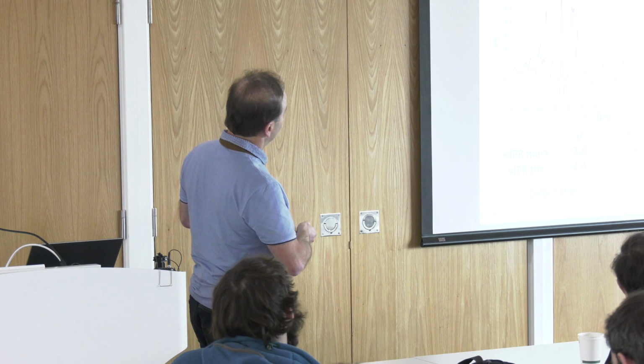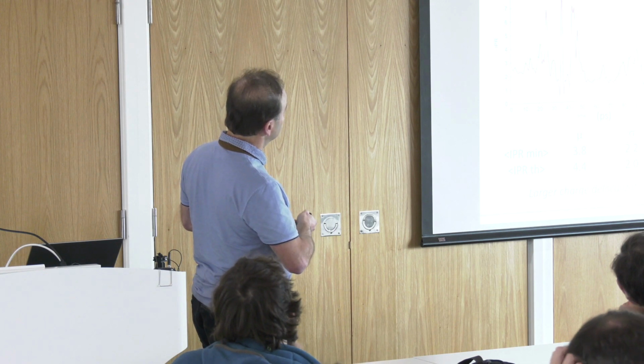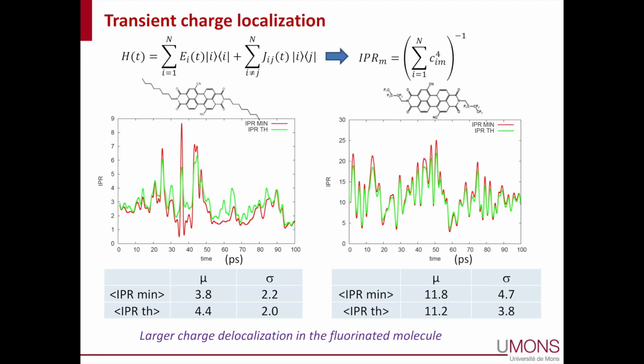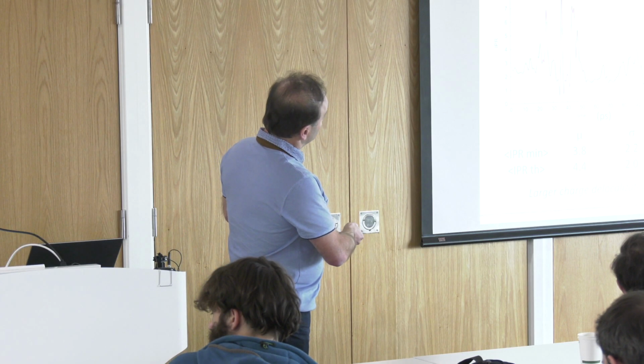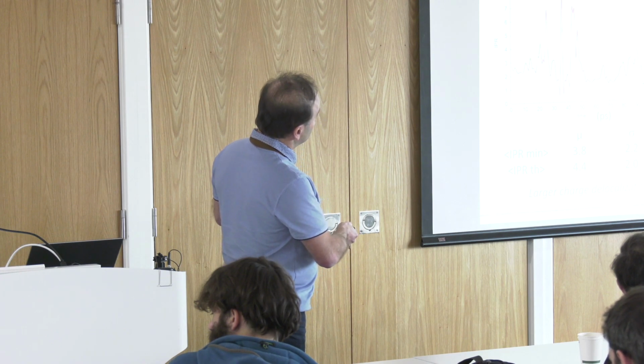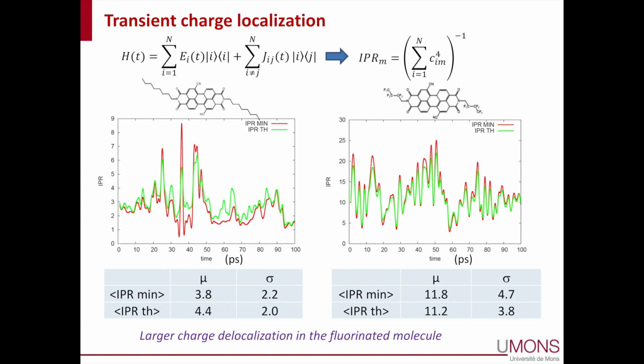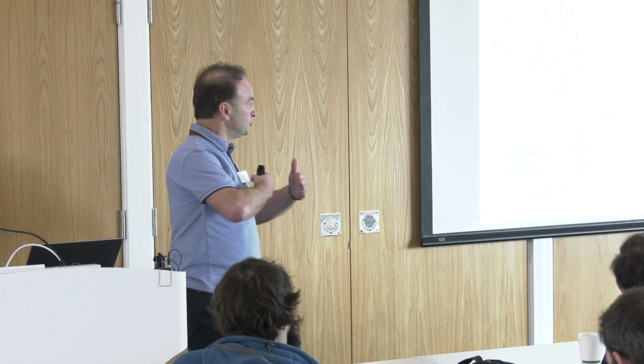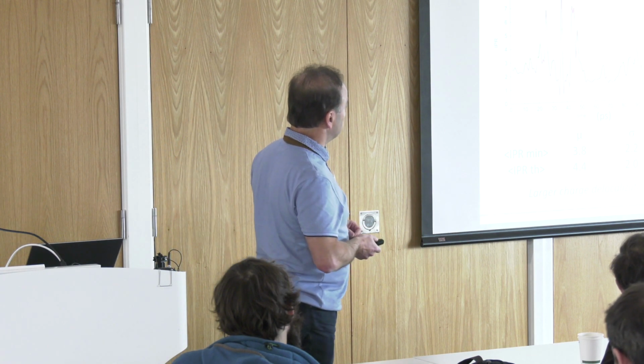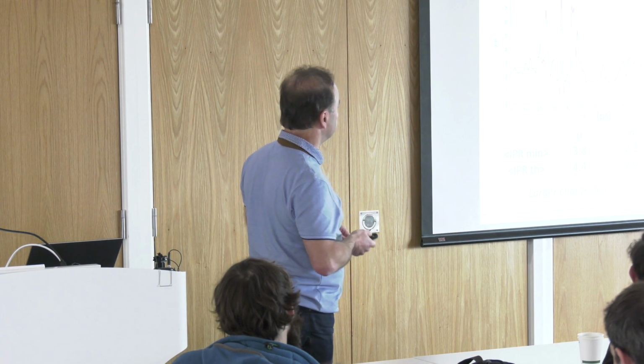And you can see that for the alkylated side chain molecule, there are large fluctuations around a small value. So the charge tends to be delocalized over no more than 2 molecules. For the fluorinated case, the average value is much higher. And this is partly because of the two-dimensional character of the transport.